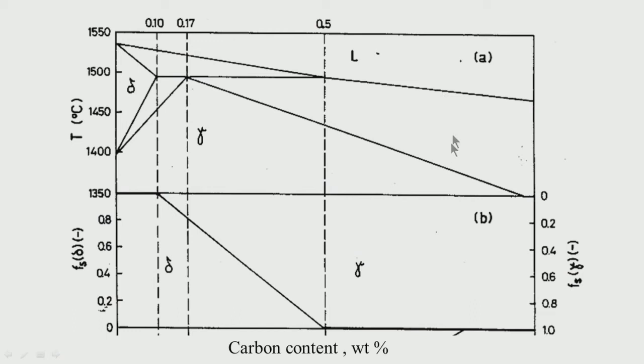And look at the solidifying range, it is quite wide. Here it is relatively less. So, you can make out that the solidifying temperatures are changing. This is the equilibrium solidus temperature. With segregation, this will become still lower. So, it will become a much wider solidifying temperature range as you are going to high levels of carbon. With more segregation, it becomes even wider.